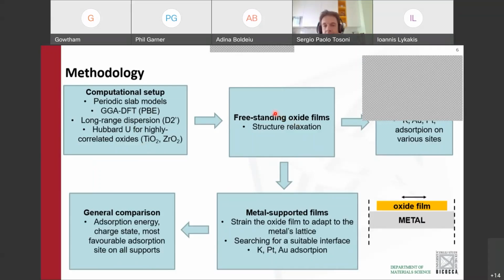And we started by studying the adsorption of the single atom on the freestanding oxide films, and then we moved to the metal-supported films. Here, as I said, a key parameter is the strain related to the fact that we have to adapt the lattice of the oxide to the one of the underlying metal, and this changes in a way the surface chemistry of the oxide film. And then we performed the general comparison in terms of adsorption energy, charge state of the atom, and most favorable adsorption site on all supports.